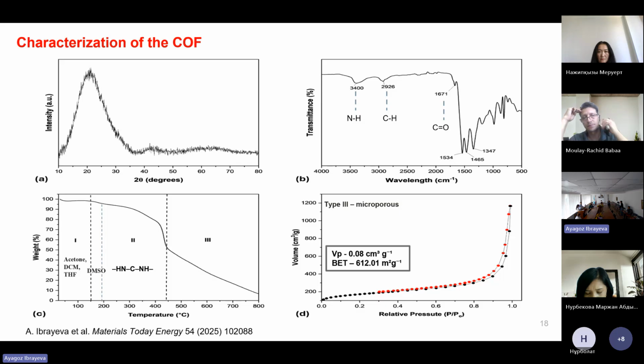By XRD, we obtain one broad peak, and according to the literature data, it is related to the amorphous structure of this material, like organic polymers. By the literature data and methods, what we synthesized, and confirmed by another XPS elemental analysis and instrumental analysis, we confirm that it belongs to the covalent organic framework materials, and present it like that in our research.